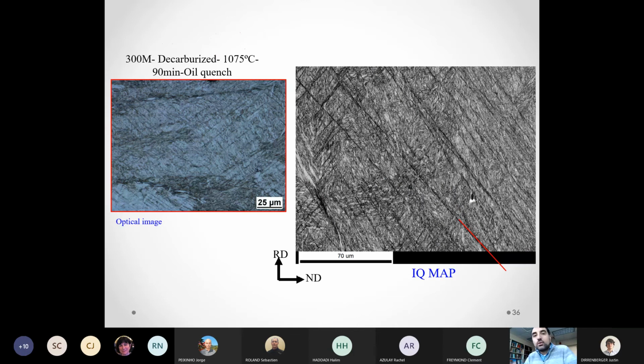We look at the microstructure of the cold rolled material and try to understand why it does not fracture. We take the material that was decarburized and we look at it at a strain of 0.5. I apologize, the strain was removed. So a strain of 0.5. And we can see on the optical microscope these tiny deformation bands. And at that point, for this strain, the orientation of the bands seems to be different from one grain to the other. That's why I call them deformation bands. And we also see them very clearly when we do an EBSD